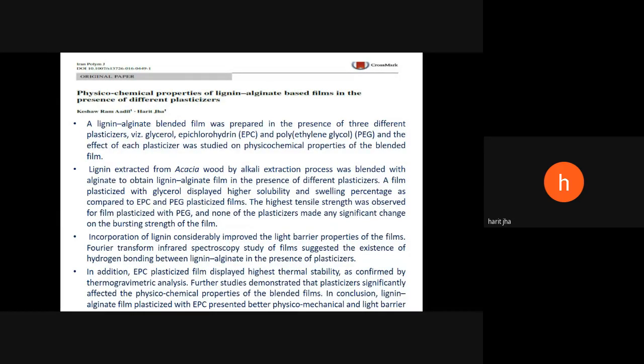Incorporation of the lignin considerably improved the light barrier properties of the film. An FTIR study of the film suggested the existence of hydrogen bonding between lignin and alginate in the presence of plasticizers. In addition, the EPC, that is epichlorohydrin, plasticized film displayed the highest thermal stability, as confirmed by the thermogravimetric analysis. Further studies demonstrated that the plasticizer